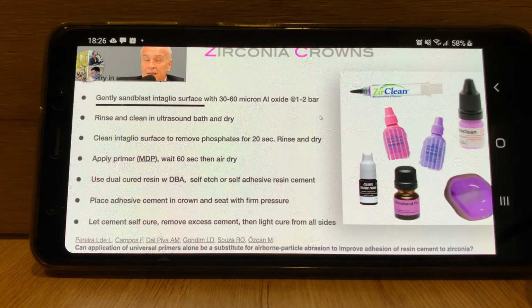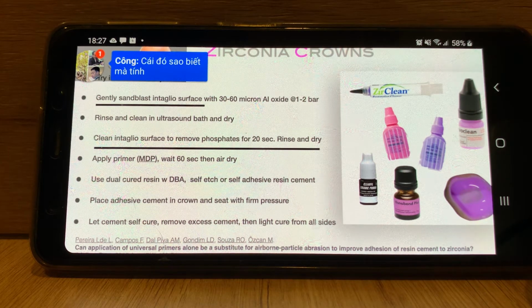And then, in this case, we need to remove the phosphates. I'll explain that in a minute. There are several ways you can do that. Then you would rinse and dry it. And then, because we are only using a chemical means of bonding to the surface, we need to apply a primer, a coupler, something that will couple the zirconia surface to the resin, and the molecule that we use for that is a phosphoric acid methacrylate called MDP. You would apply it, let it air evaporate for 60 seconds, and then air dry it with clean oil-free air. Once you've done that, you can apply your cement.